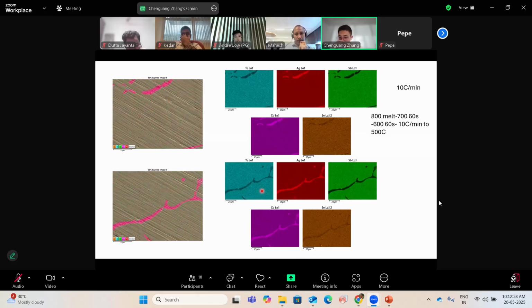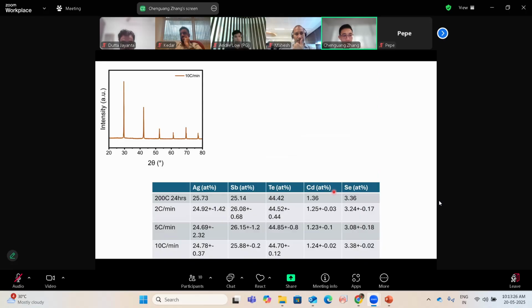Yeah. And then this one is 10 Celsius per minute, a faster cooling than before. So you see the interface layer is wider than the 5 Celsius per minute and the 2 Celsius per minute. And the mapping is quite clear, at least from the same recipe. But for the XRD here, sorry, I don't have much XRD slot, so I have to give it a quick scan.